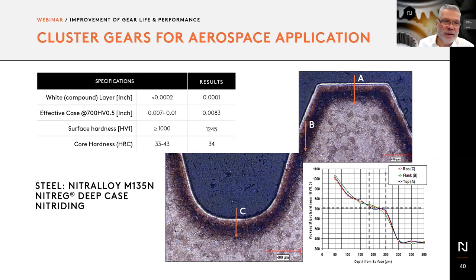One of the examples here is specifically a cluster gear for aerospace. To the right-hand side, at the bottom, what you see, and one part of the evaluation, is the uniformity of the case throughout on all sides of the gear. So you have it at the root, flank, and top, but also a very high hardness, in this case over 1200 Vickers, as well as a very, very thin white layer, which is almost nonexistent in this case. Obviously, this is a Nitralloy, and Nitralloys specifically produce this type of hardness gradients.